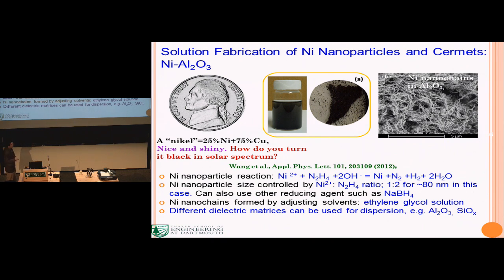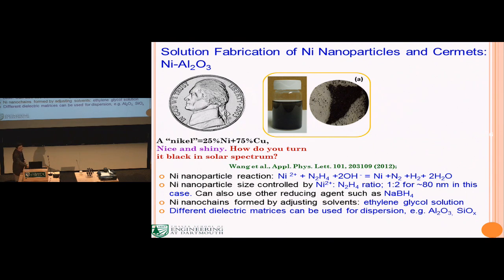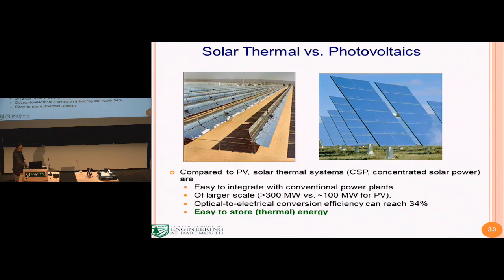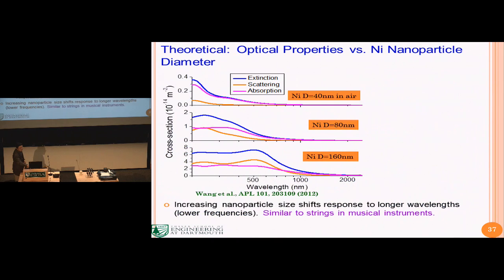For example, here I showed that if you just have single particles in the air, you can have this absorption edge around 1 micron. If you want to redshift that to longer wavelengths, you can use the nanochain structure.